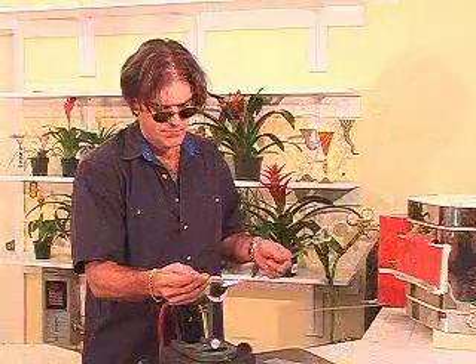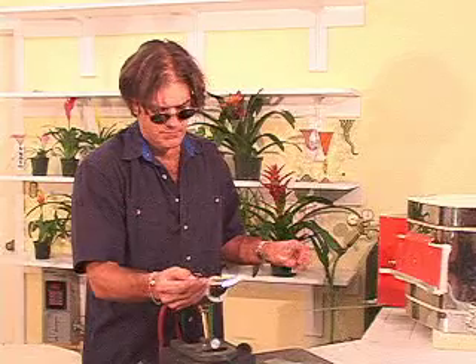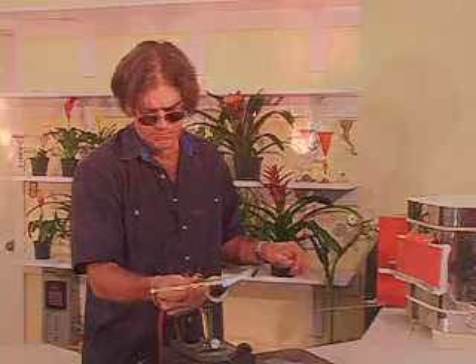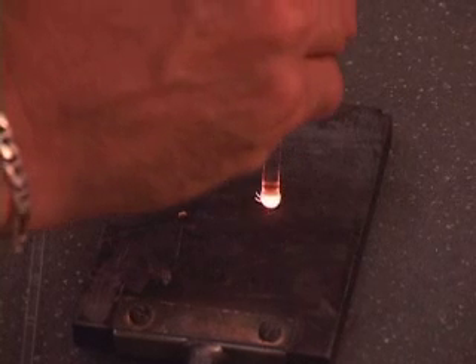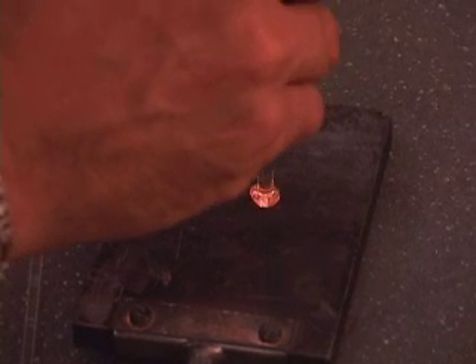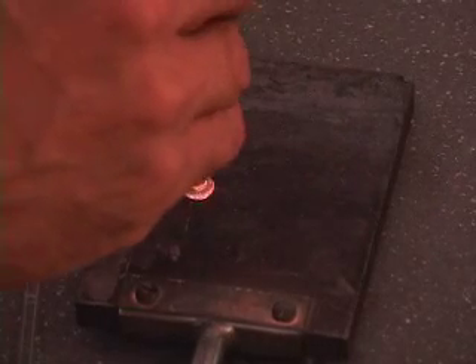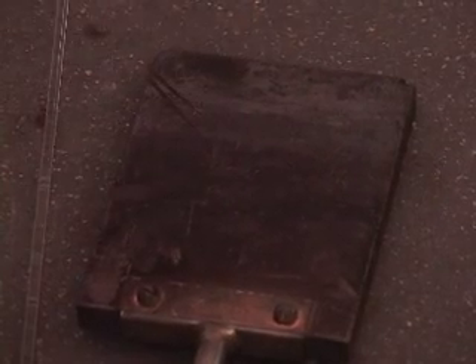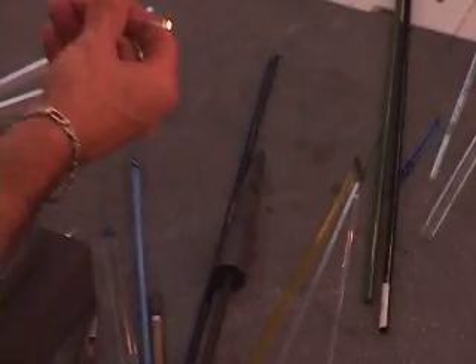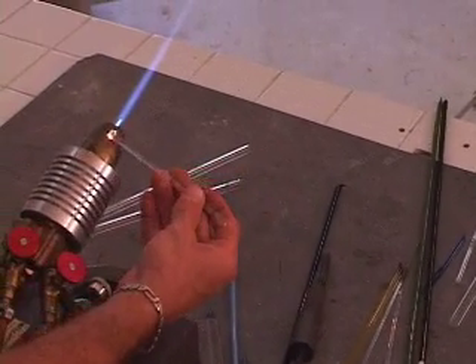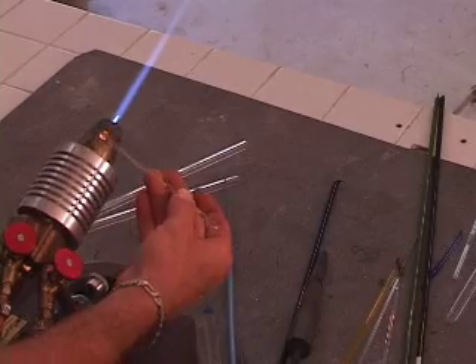Take two 10-inch 5mm rods and preheat the tip of one rod. Pick up a small piece of fine silver. I use bezel wire. Preheat the second tip and pick up a piece of 22-karat gold. Press the molten glass on the torch to push the precious metal to the tip of the rod.